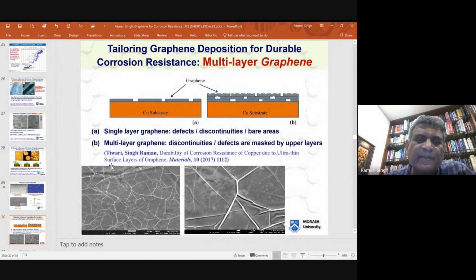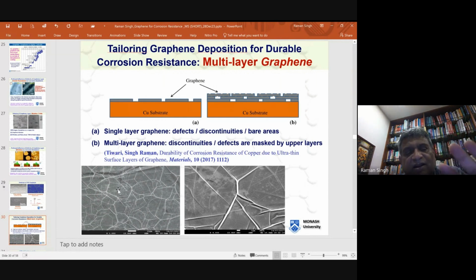So when the first student joined to work on this project, we came up with a hypothesis, that if we have multi-layer graphene in place of single-layer graphene, that could be better for corrosion resistance. And the reason behind that hypothesis is very simple: if you have single-layer graphene, you may have disruptions, and at the site of disruption, there will be greater corrosion happening because of cathodic nature of graphene. But if you have multi-layer graphene, then it is likely that the disruption in the first layer will be masked by the upper layer, if not one, by the second layer. So with that hypothesis, in fact, we showed that you can see there are wrinkles in the lower layer, but where you have wrinkles in the lower layer, that is masked by the upper layer, which may itself have wrinkles. So that was the purpose of the hypothesis.